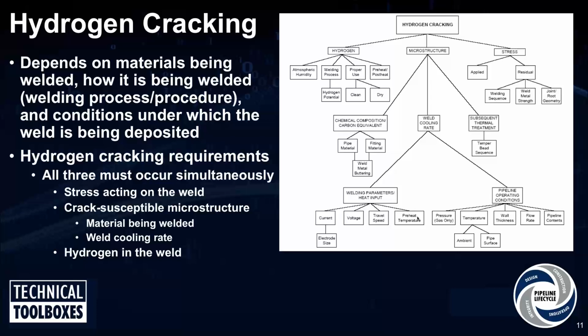So that's where the hydrogen comes from. The microstructure of the weld is really affected by the material that you're welding and how that weld cools. Now again, you're doing in-service welds, so you can't really control the material you're welding, because it's again pipeline in the ground. But what you can do from a welding standpoint is control how that weld cools. Again, this goes back to the balancing act between how much heat goes in versus how much heat goes out. So if you have more heat going into the weld, then that weld will cool slower. Welds that cool slower tend to have a non-brittle microstructure.